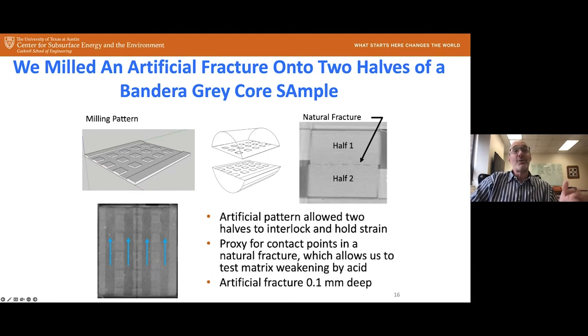So we did something that an engineer would do, and if you're a geoscientist, maybe you'll cringe a little bit at this approach, but we thought it worked pretty well. We took these two core halves and then we milled a pattern into them where we have these raised asperities. And these raised asperities are each about 0.1 millimeter tall, and we have these on either side of the core halves. Then we lock those in place and do our displacement under compressive pressure, and then induce that strain in that way. And now it holds and then is released over time. And so the idea is that the points where these asperities interlock with each other, that's similar to where we have contacts in a natural fracture and where they're holding that strain and looking at how that is released over time. But now we're doing it in a reproducible way, and one that we can have replicate experiments for.